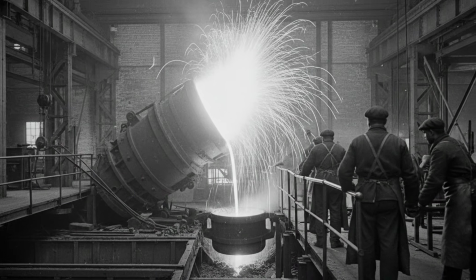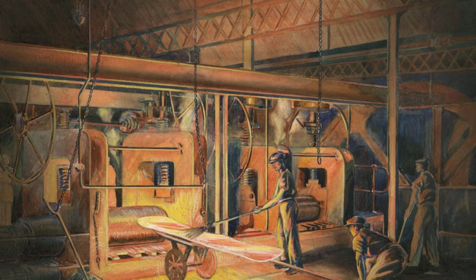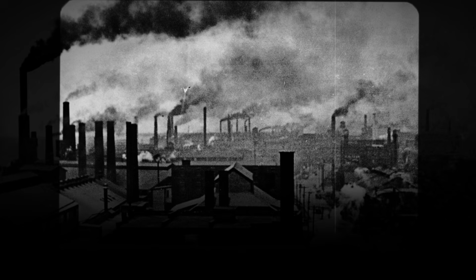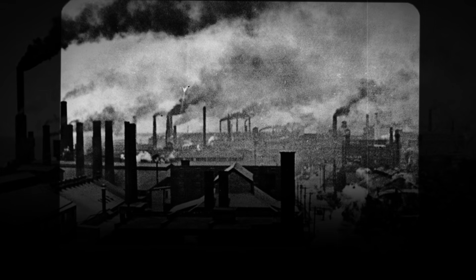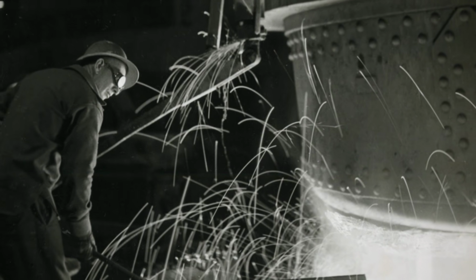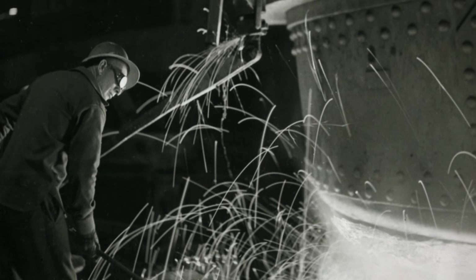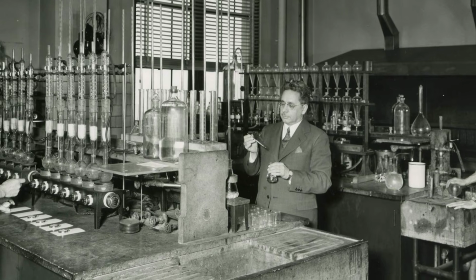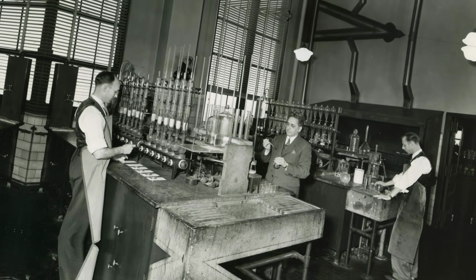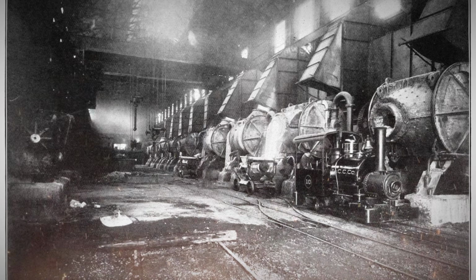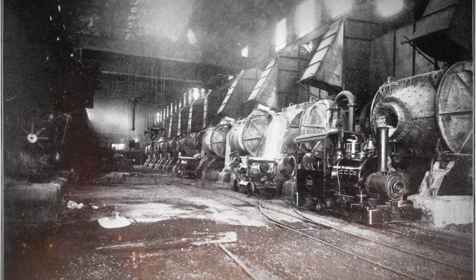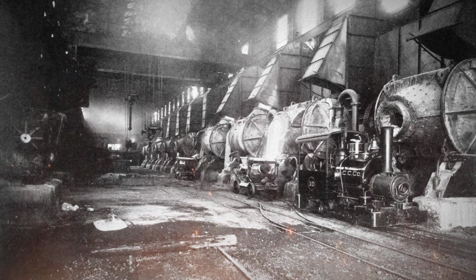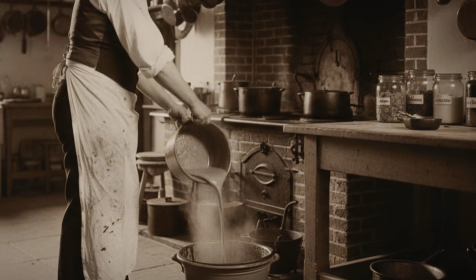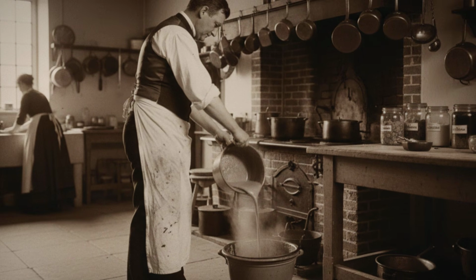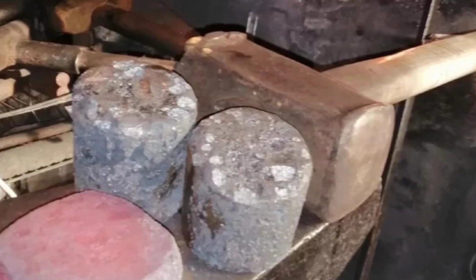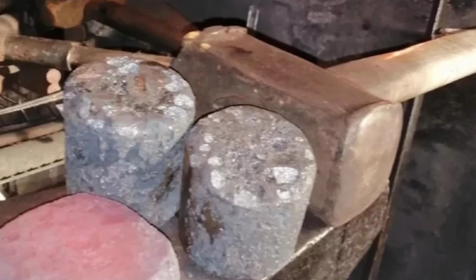The Bessemer kept blowing. The process began to be replaced by the open hearth furnace in the 1890s and the 1900s. Open hearth furnaces were slower, but produced higher quality steel and allowed for better chemical control, which became more important as the products steel went into became more demanding. The Bessemer process had an inherent limitation. The blow was so fast, typically 20 minutes, that there was almost no time to sample the steel and adjust its composition mid-process. You were essentially committing to whatever the iron's chemistry gave you and correcting afterward.